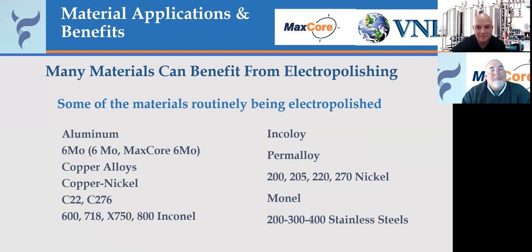Yes. So I don't understand your question. Well, a lot of times we'll have somebody say it's 32 RA, and if you just EP it, it's going to go to 20. I see where you're going. Yes, absolutely. Electropolishing will reduce the RA value, depending on the material that you're electropolishing, in most cases typically by about 40%.